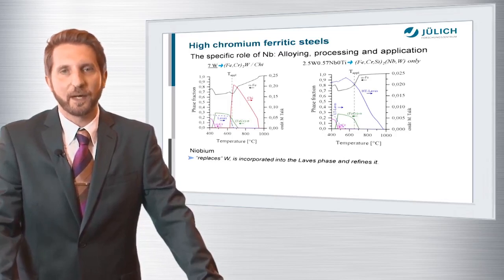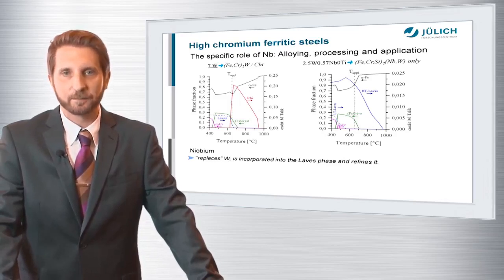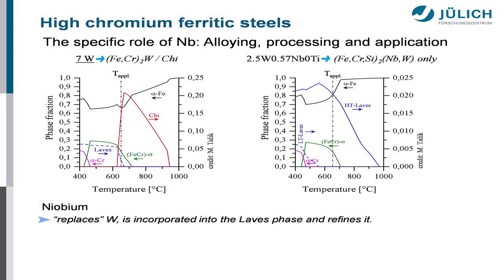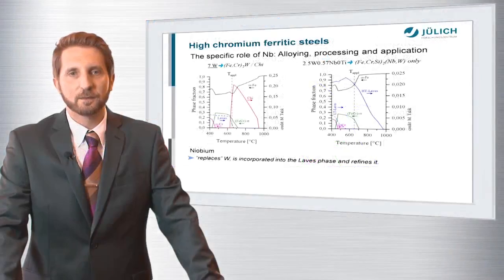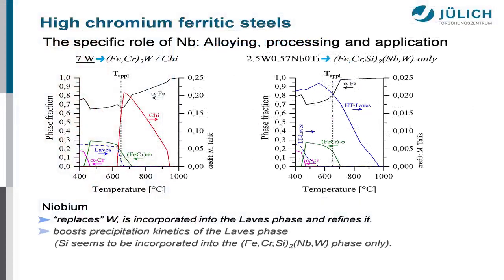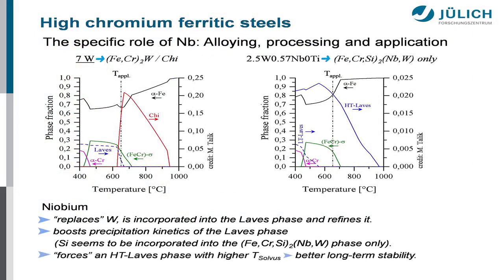If you go, on the other hand, for combined alloying with niobium, like it is shown on the right-hand side, you see that very small amounts of niobium are already sufficient to really reach reasonable creep strength in these materials. And this is for the formation of this mixed Laves phase that I already mentioned some slides ago. So frankly speaking, and to keep it simple, niobium replaces tungsten. It is incorporated into the Laves phase and refines it. It forms smaller particles. Furthermore, it boosts precipitation kinetics of the Laves phase. It forms a so-called high-temperature Laves phase with a higher dissolution temperature. That can be seen on the right phase diagram.